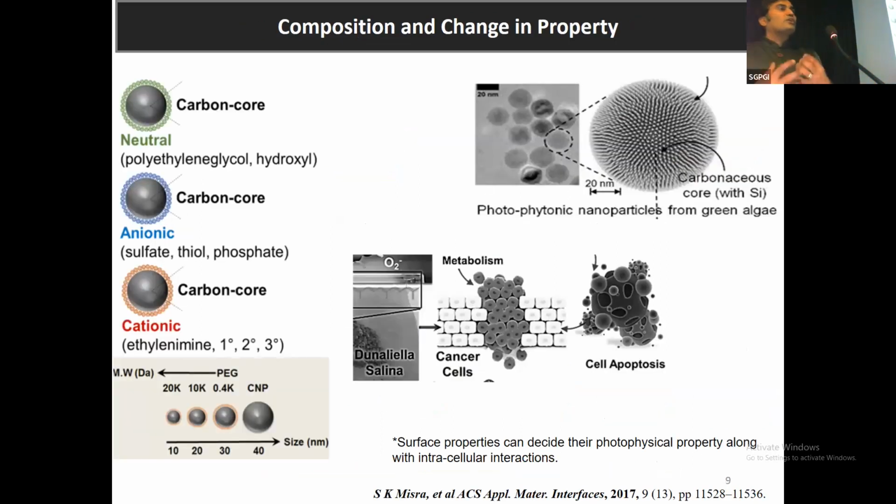Now, what if you want to use the intrinsic property of some medicinal plants and you don't want to extract that medicine or active component from the plant, but still you want it to be incorporated in the nanosystem? You use that raw plant part. It could be a leaf, stem, roots, any part of the plant or the plant as such, and then convert it to carbon nanoparticles. You'll find that many of those particles will inculcate that medicinal property. Now there could be a question: what about the heat you are generating or the microwave you are exposing it to? That might degrade the medicinal value of that particular active component. So this is a very genuine concern. The option is that you do microwave preparation. Many of these thermolabile materials are stable in microwave.